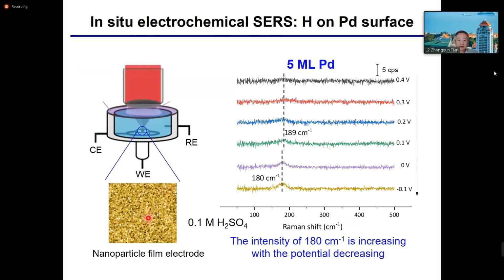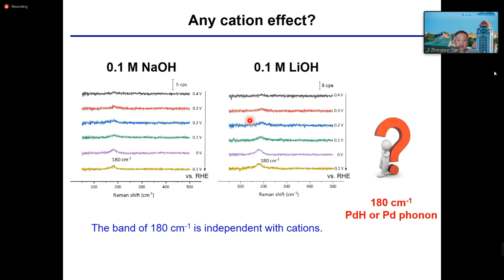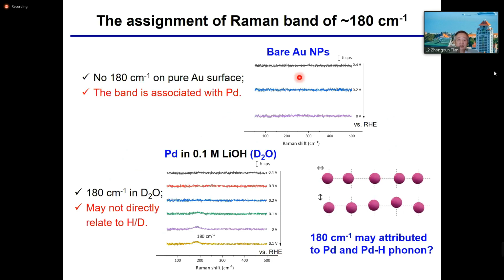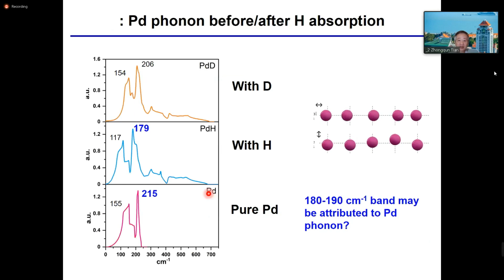As you can see, we can perform the spectro-electrochemical measurement on this gold nanoparticle coated with palladium. Then we can see those low frequency bands, which we never observed before. It's quite interesting, and it gets relatively stronger when the potential is close to the underpotential deposition of hydrogen. We changed the cation to see if there is any effect, but there was no effect. Then we checked the bare gold nanoparticle: no signal at all. Then we went to deuterium, and surprisingly this band does not change. They only change with potential, especially at the threshold of the potential deposition of deuterium or hydrogen.